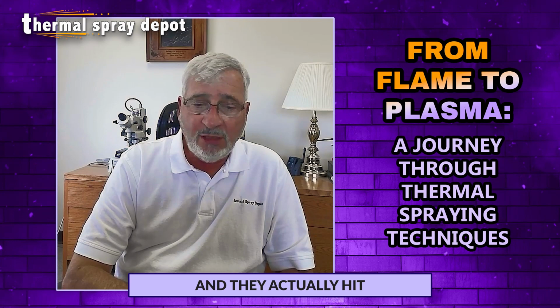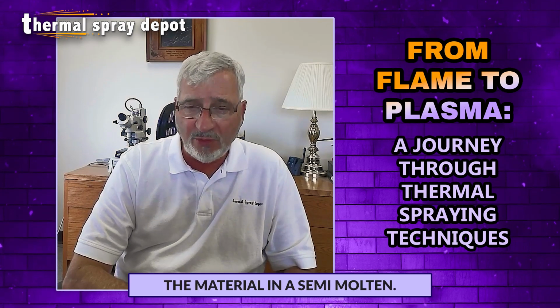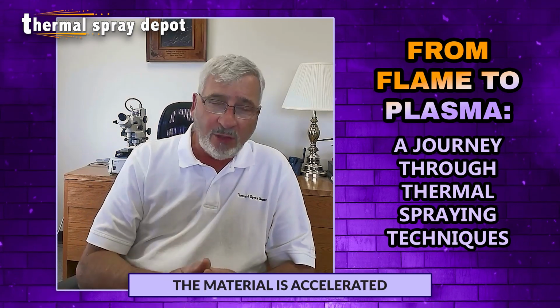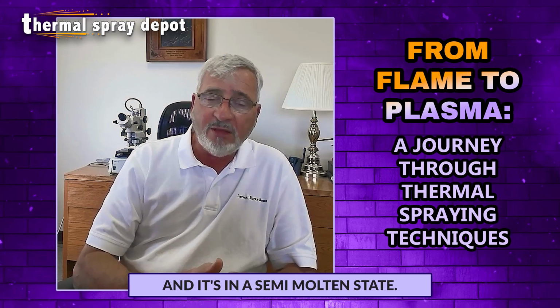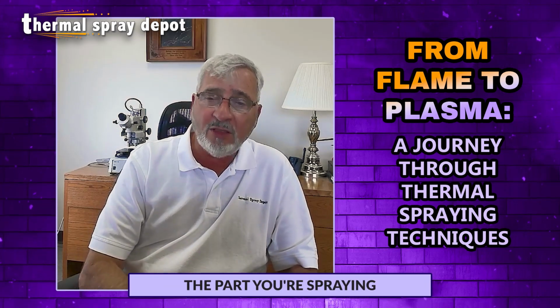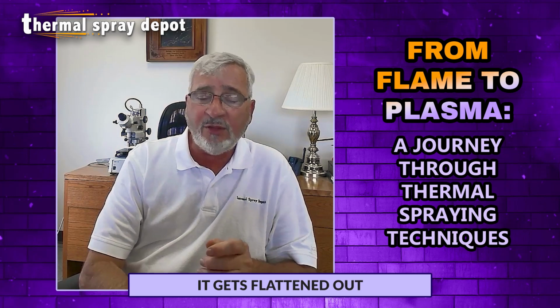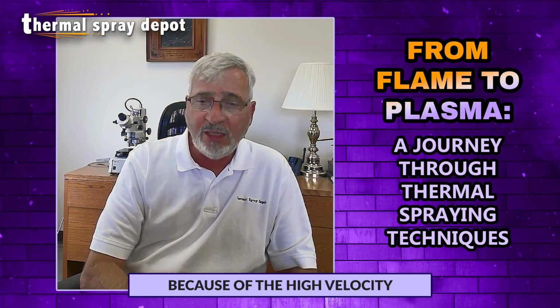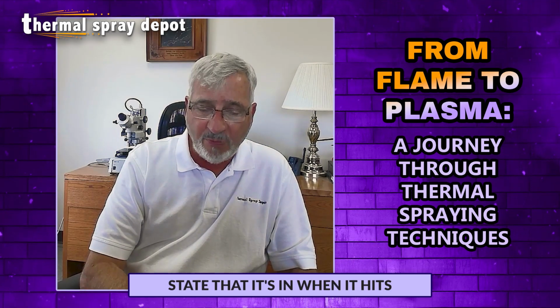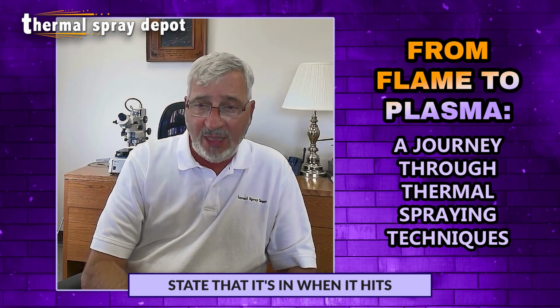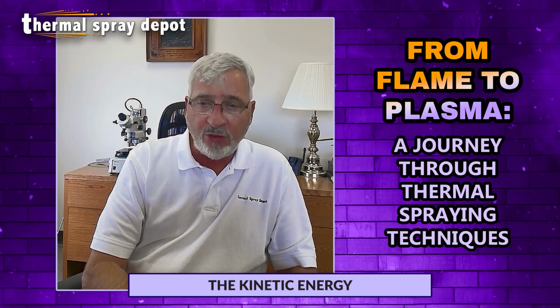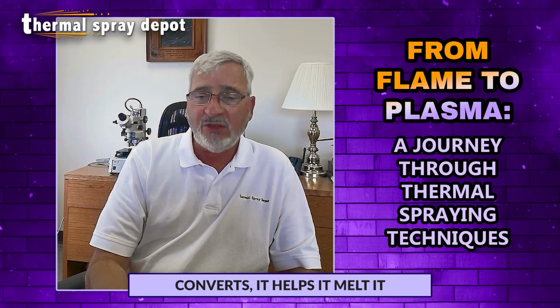The material is accelerated and it's in a semi-molten state. And when it hits the part you're spraying, it gets flattened out because of the high velocity and the semi-molten state that it's in. When it hits, the kinetic energy from the velocity converts it and helps melt it.